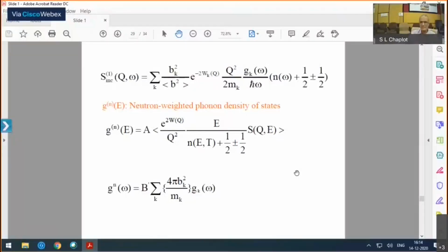It is only maybe the Debye-Waller factor or some standard instrument parameters, which can be more easily corrected. So vanadium is often used as a standard sample for calibration of the instrument, and with respect to that we can see how these intensity corrections can be made, coming from all kinds of factors.